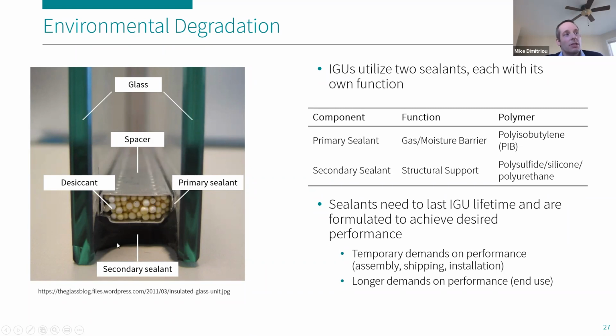And then to lock everything in place, you need to provide a sealant that holds everything together and keeps the interstitial space sealed. In some IGU constructs, this is typically achieved by using two sealants, a primary sealant and a secondary sealant. And the reason being, both sealants provide you with a different function, which in combination gets you to your IGU function. The primary sealant is added because it has excellent barrier properties. It essentially stops any gas or moisture from moving in or out of this interstitial space. And that's something you want. The last thing you want is moisture to come inside between your two panes of glass, to condense onto a surface and be something that you can't access to clean.